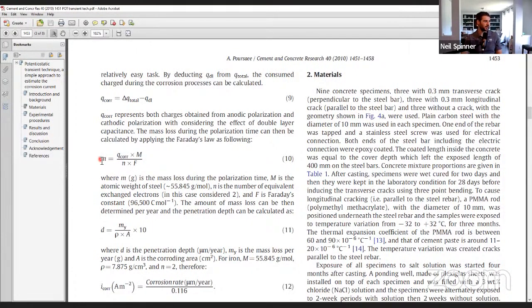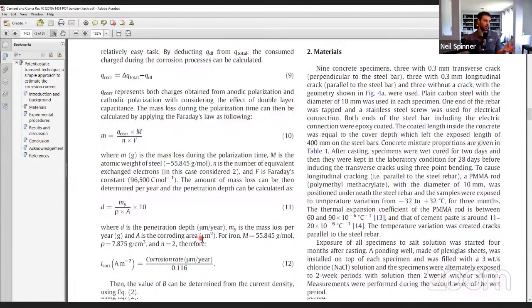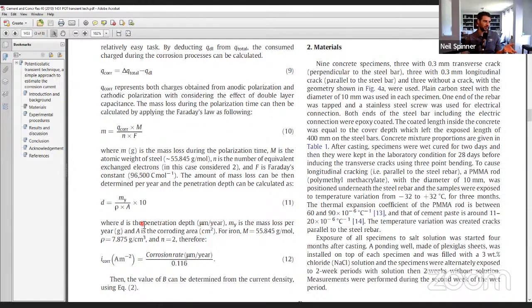Okay, and so this is a version of Faraday's law of electrolysis. Okay, this right here, m = Q times M over nF, this is Faraday's law basically. And so this transient technique is another way, in addition to linear polarization resistance, to get at the corrosion current, which gets you your corrosion rate, which is sometimes called penetration rate or penetration depth. And it's like how much of your material is decomposing over a period of time. That's all I'll say about the transient technique, so as to not take too much time on that.